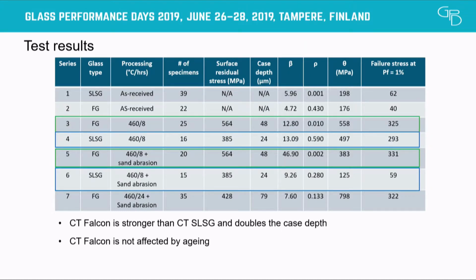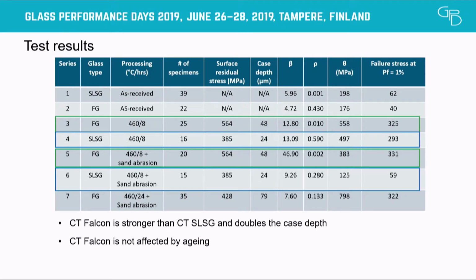For example, let's compare now Falcon glass as chemically tempered and with the sand abrasion. You see that the failure stress at a probability of failure of 1% goes from 325 to 331. Considering a confidence interval, we are talking about essentially the same value. If instead we look at soda lime glass, we go from 293 to 59 megapascals. This, to some extent, confirms the work done by my colleague Corinna in Cambridge, but also tells us that the case depth is very crucial. Indeed, if we go back to the column where case depth is shown, we got 48 microns for Falcon glass and 24 microns for soda lime with the same time of chemical tempering.